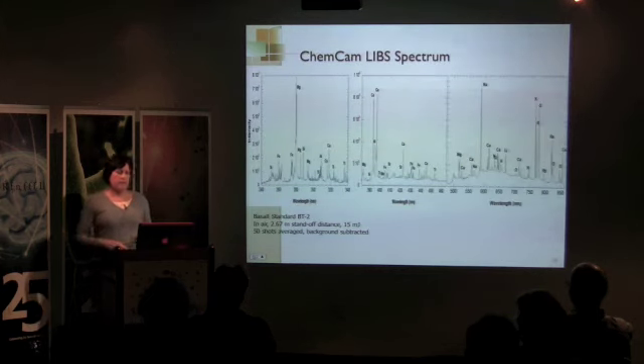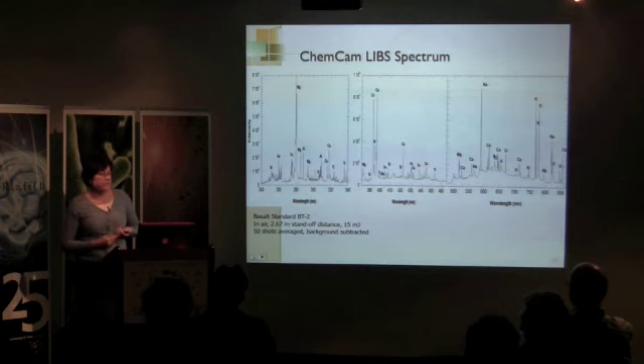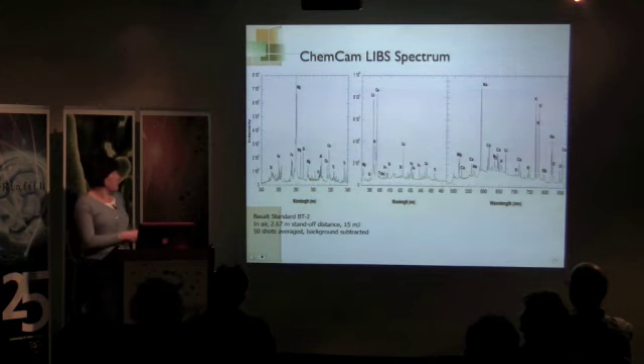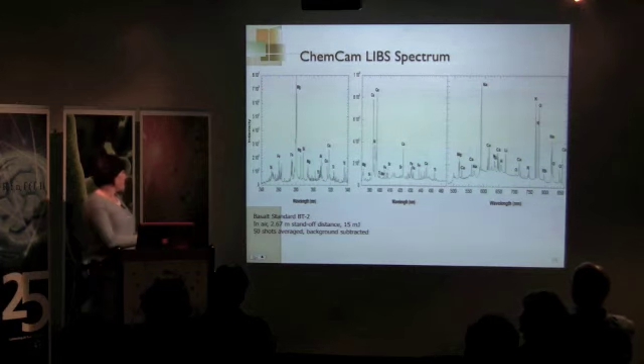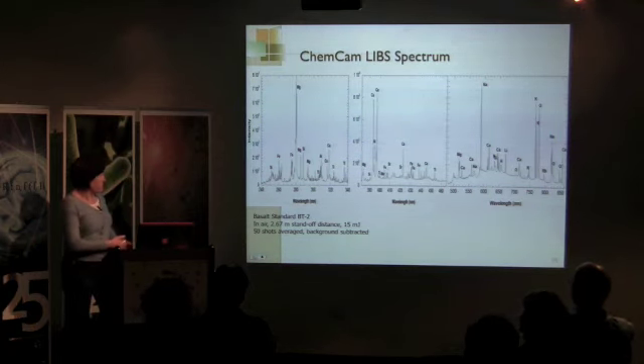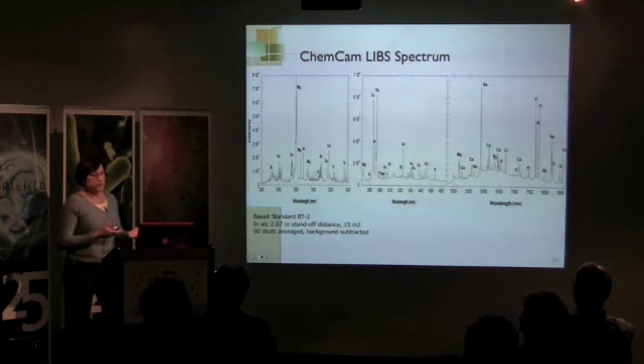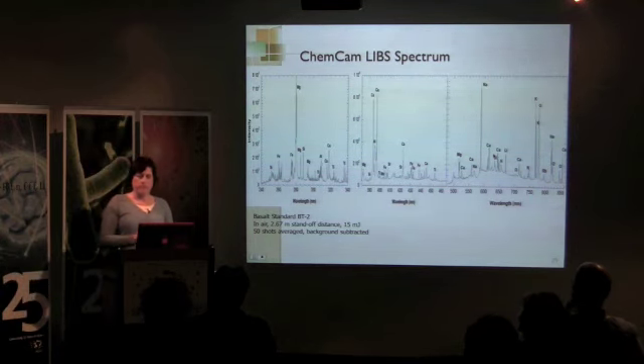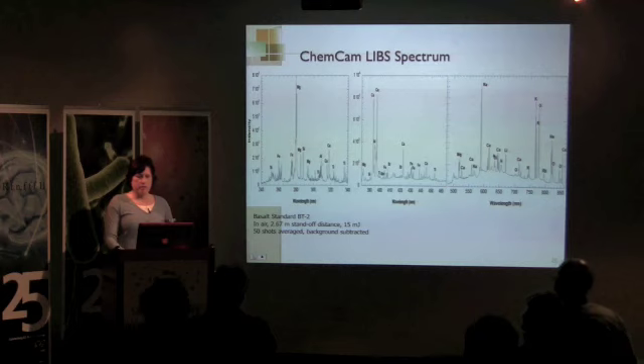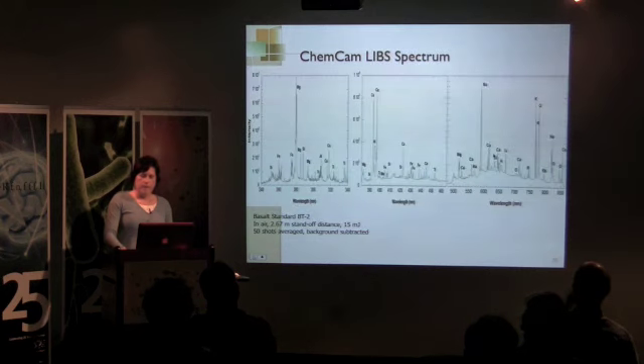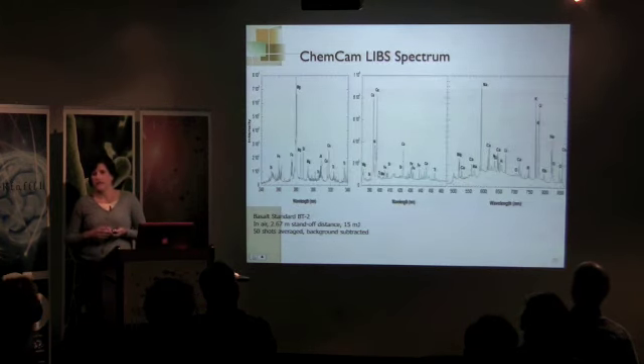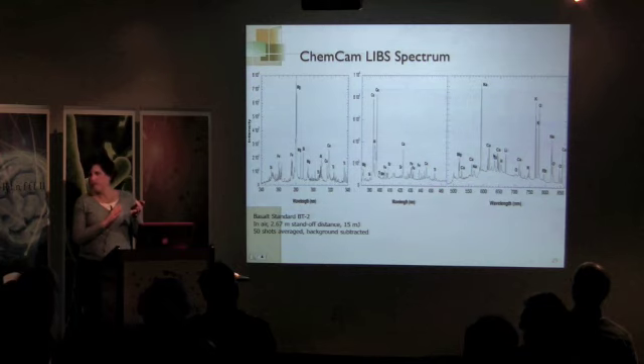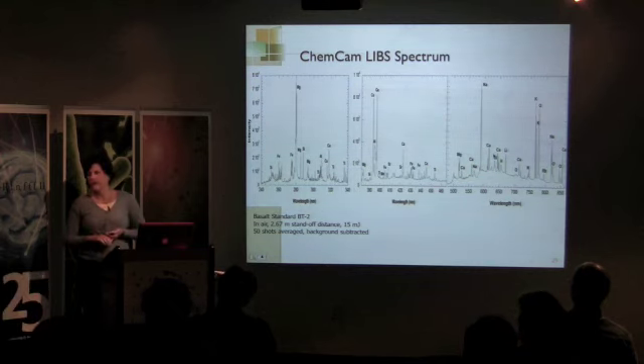All right, now I'm going to talk about some of the measurements we've been making. Here's a typical LIBS spectrum showing the full spectral range we can cover. I've sectioned it off by spectrometer, 1, 2, so you can see there's a few gaps in wavelength. And this is actually a spectrum collected of basalt in air. And what we've done is we've taken 50 shots and then averaged them to come up with this final spectrum. So once we have the spectrum, to get essentially the characteristics of our sample, we have all the information for the different spectral lines, and we can categorize those and get a quantitative evaluation.